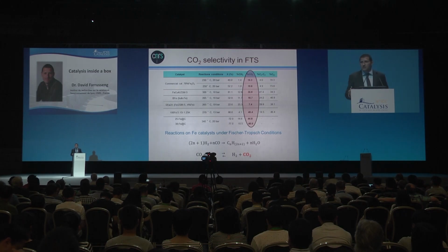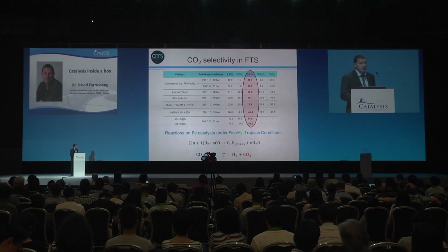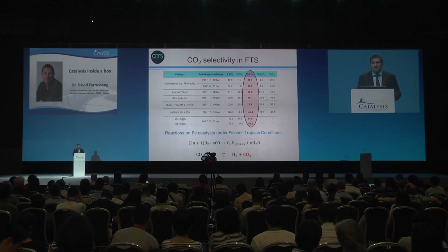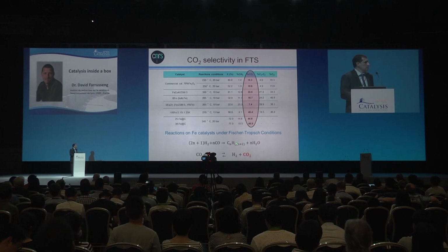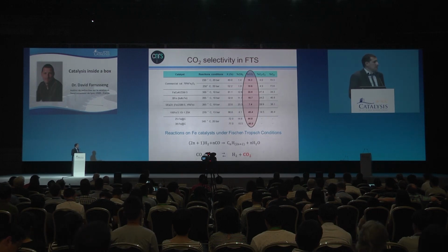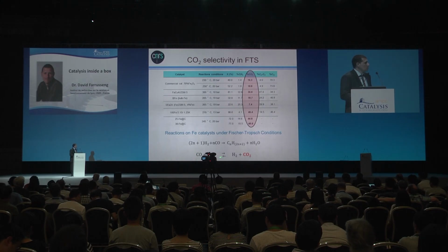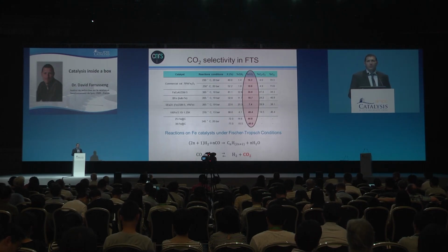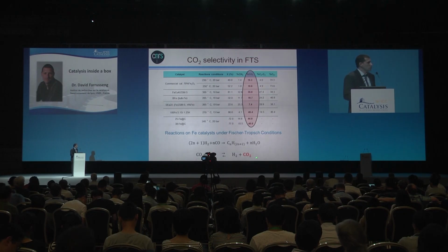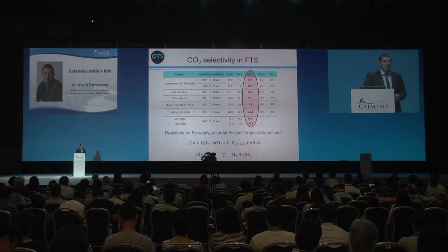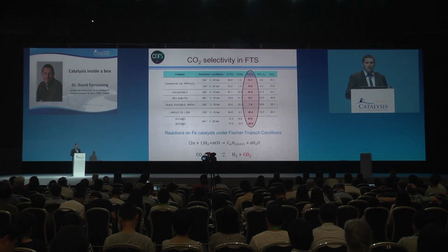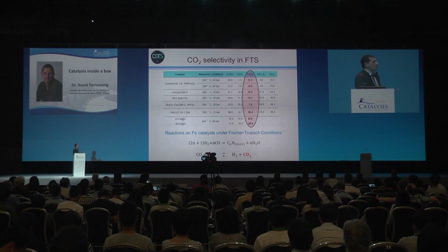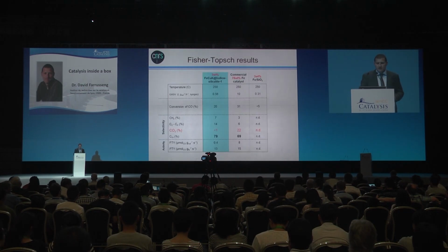And it is expected because in the Fischer-Tropsch reactions, you produce obviously the oil, the alkanes or C5 plus fraction if you want, and you produce a lot of water. And in a parallel reaction, the CO reacts with the water in the so-called water gas shift reaction to produce CO2. And iron is known as a very active water gas shift catalyst. So it's obvious that we can expect a high amount of CO2 in all types of iron catalysts.